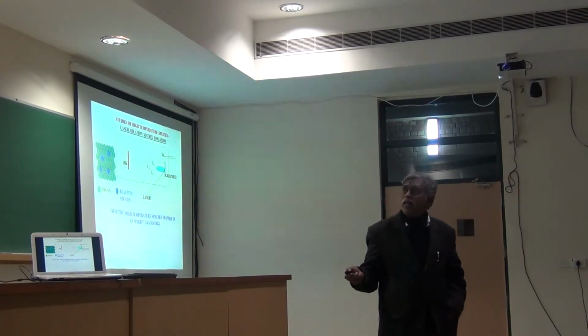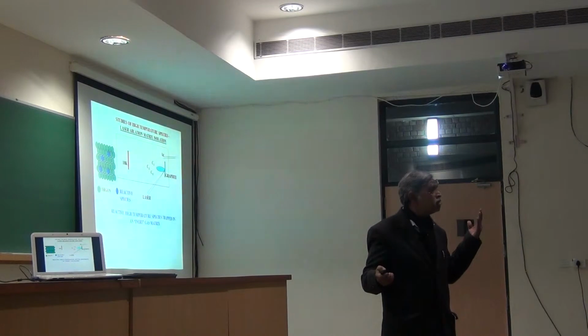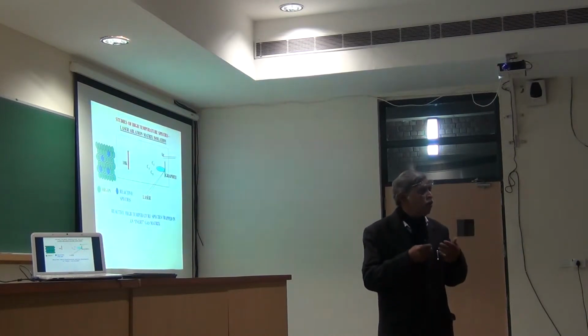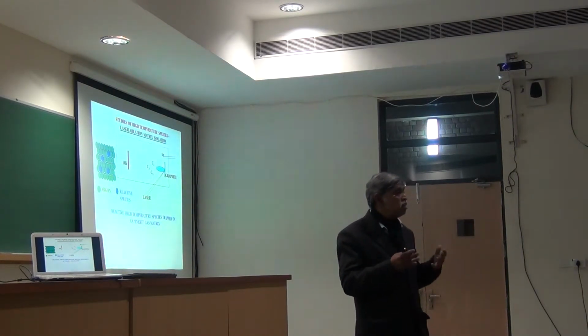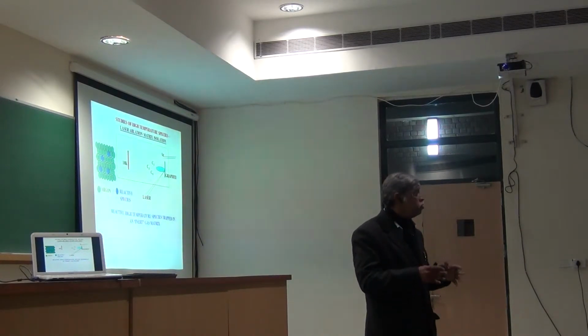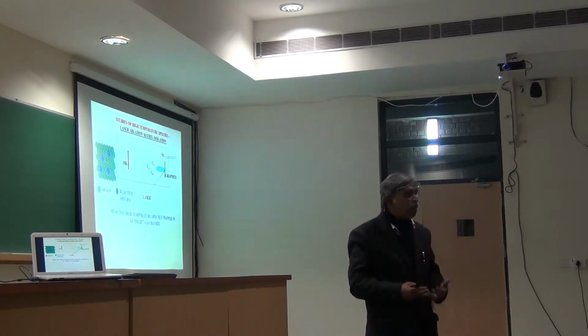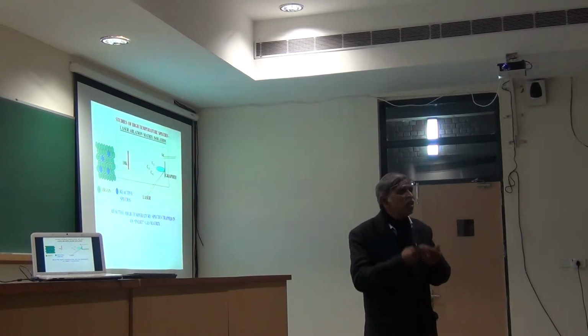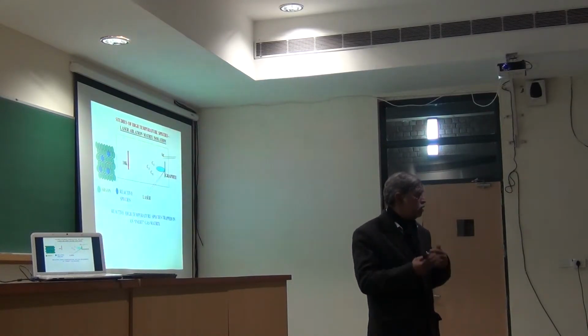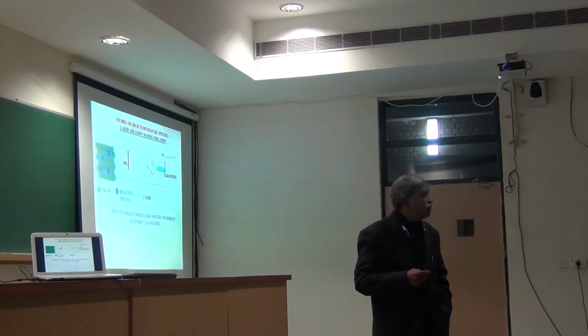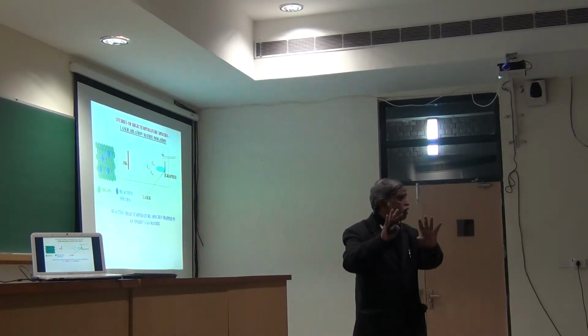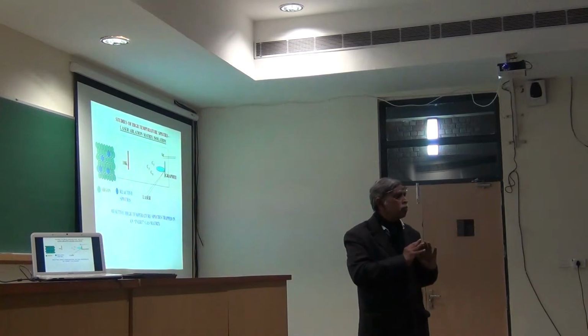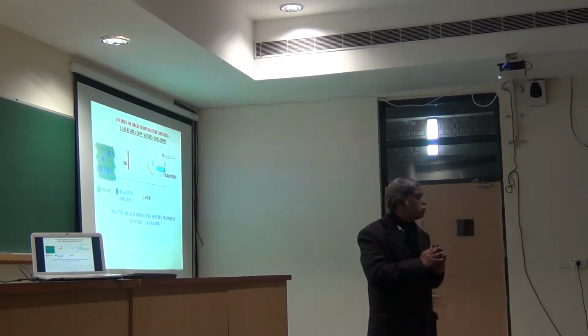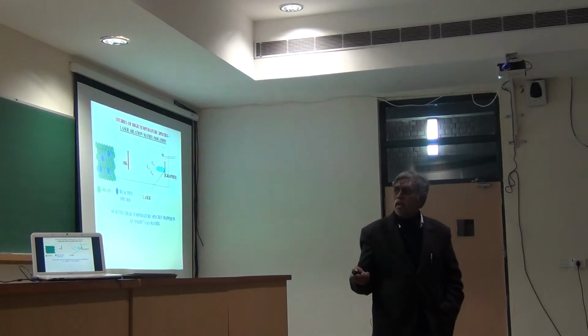And of course, now if you go and take this sample and record an infrared spectrum, what's the infrared spectrum you're going to get? You're going to get the infrared spectrum of all these species, very reactive, and which have all been produced at 4,000, 5,000 Kelvin and so on. So you basically have information on high temperature species, but you're using a low temperature technique to do that. And that's the whole idea of the title, low hot, low cold. Having hot species trapped in a low temperature sampler that we basically have produced in this experiment.